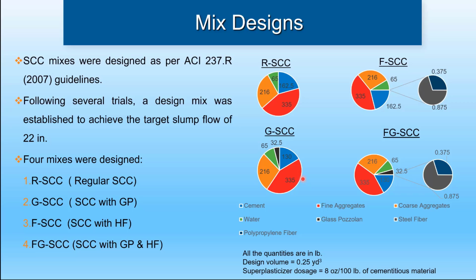And once we had obtained that, 4 mixes were designed. That is the R-SCC, the regular SCC; the G-SCC, SCC with glass Pozzolan; the F-SCC, SCC with hybrid fibers; and the FG-SCC, that is the SCC with glass Pozzolan and hybrid fibers. On the right of the slide, you see the composition of different materials used to formulate these mixes.